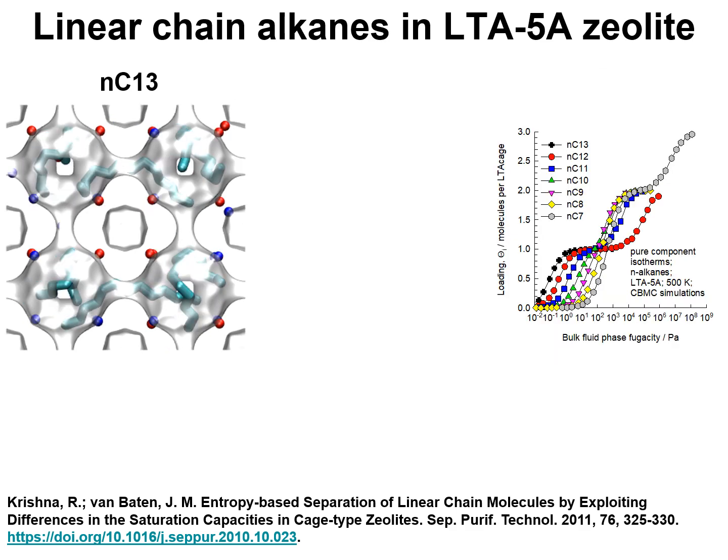For the adsorption of NC13 alkane in LTA-5A zeolite, the saturation capacity is just 1 molecule per LTA cage. And we indeed see the snapshots that confirm that the maximum cage capacity for NC13 is 1 per cage.